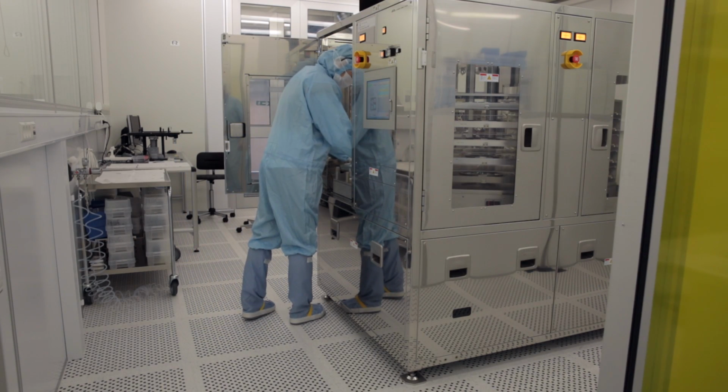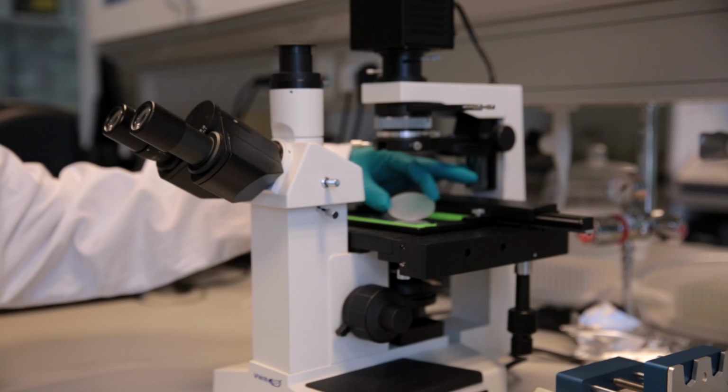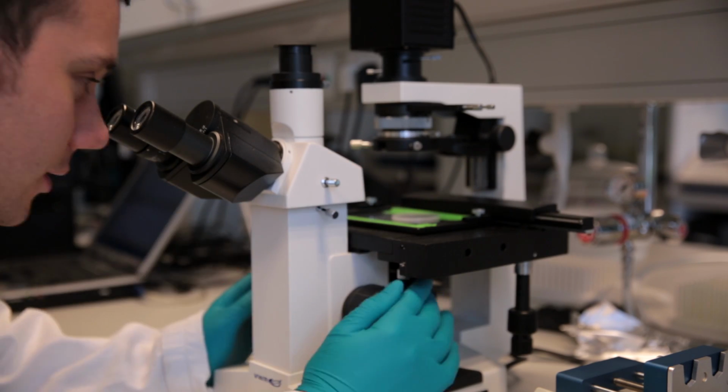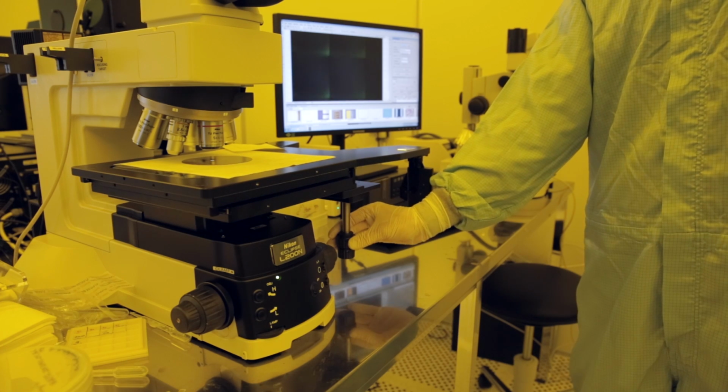There the nano pattern can now be transferred to the mold by NanoImprint lithography. We have developed a technology for making nanolithography on the injection molding tools. And this both includes a NanoImprint technology where we can create the first pattern in a thin film of polymer which is coated inside the tool cavity. We have also developed methods for transferring that pattern into the steel either by etching or electroplating on these complex surfaces. Well, the main challenge of the project is to apply the nanotextures in some areas of the mold when the geometry of the part is complex.